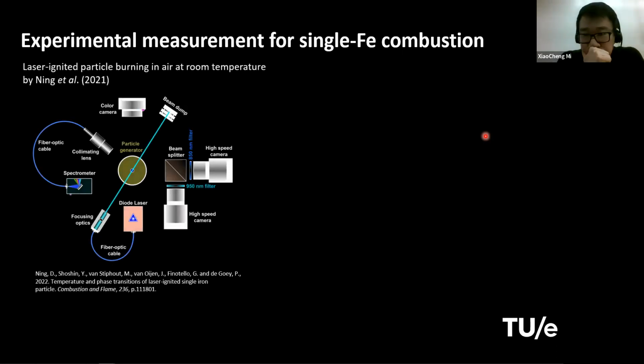So the two sets of experimental data I'm going to talk about are both from single particle combustion experiments. The first one was obtained by a former PhD student at TUE, Ning, and his colleagues. He used this laser ignited particle reaction system. This is a top view of the burner, and the particle is emitted from this center point, coming out of the page, and then it is heated by a laser. The laser can ignite the particle, and then the particle's trajectory and its combustion process are recorded by cameras, and the temperature can be measured through this two-color pyrometry system.